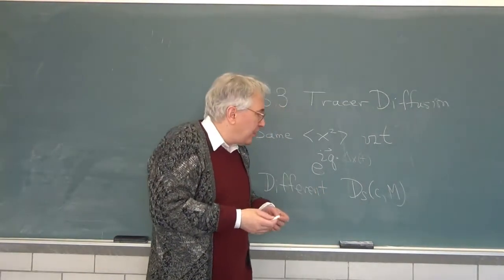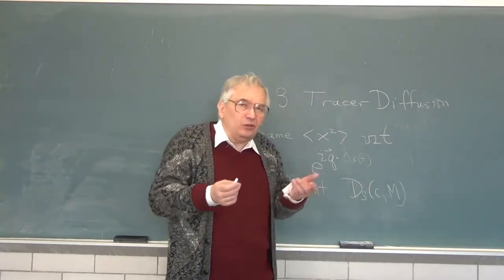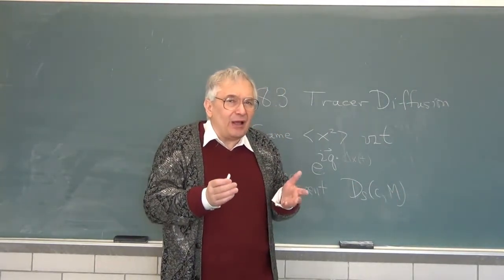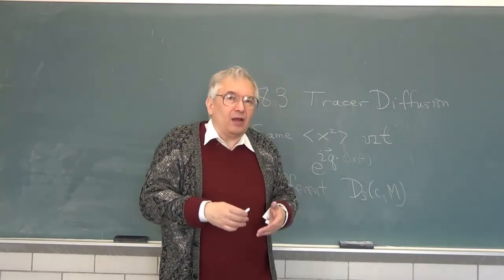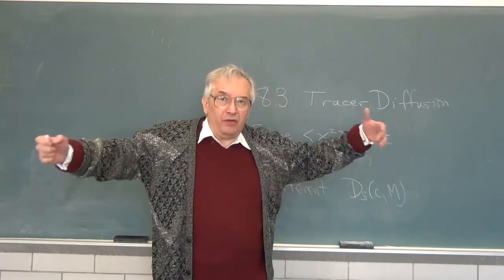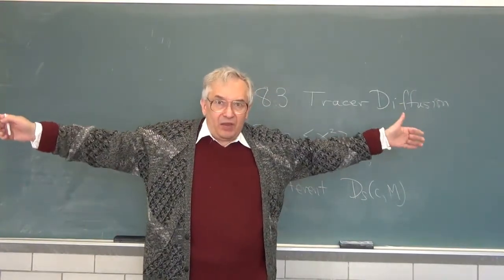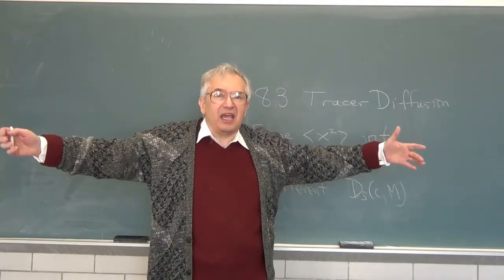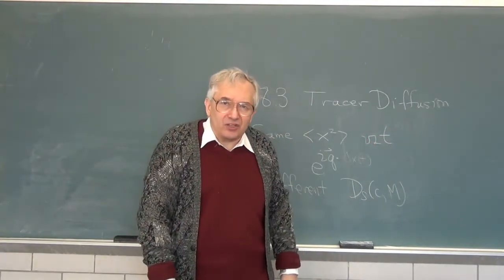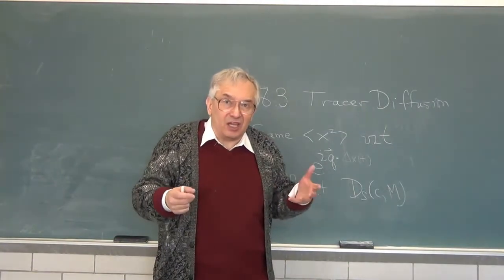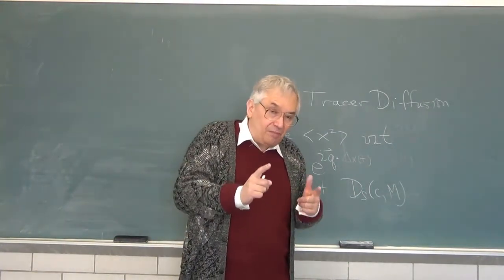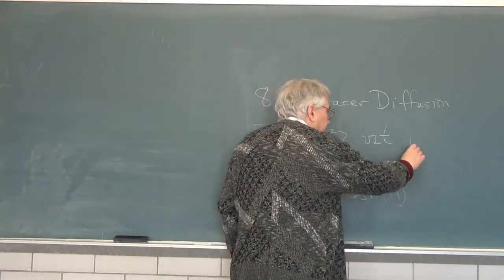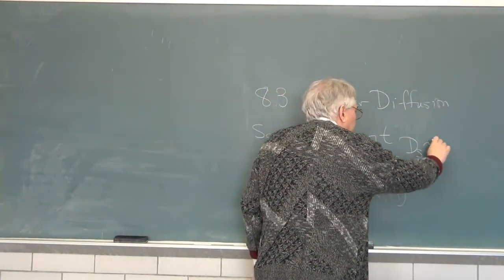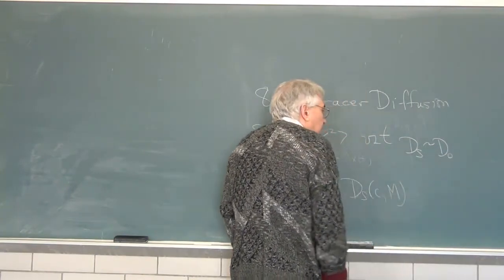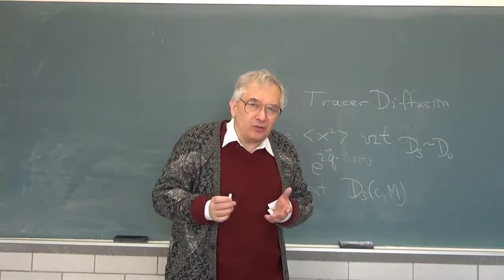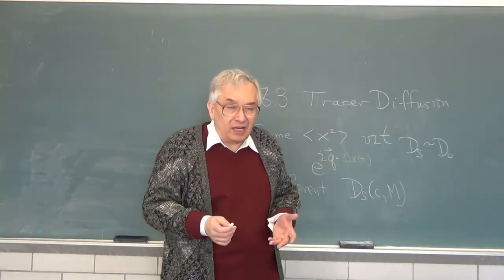Well, that's very interesting. Why does the solution become more effective at slowing down the polymer that's trying to move? One could imagine the answer is, I'm the diffusing polymer, I'm getting bigger and bigger, and therefore, in some sense, I get attached to more and more things, and the resistance increases because the moving object is getting bigger. That's incidentally beyond the statement that the diffusion coefficient in concentrated solution is proportional to the diffusion coefficient at high dilution.